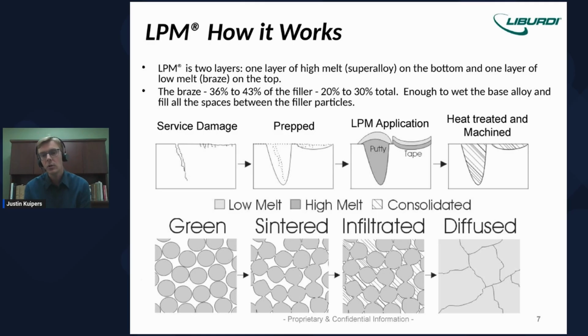We then heat treat to a temperature where our braze has melted, but the part and the high melt powder have not melted. At this point, when our braze becomes liquid, it flows into the spaces between our high melt powder particles and fills those voids by capillary forces. We then go to an even higher temperature where we get consolidation and homogenization of our repair joint, and we get solid grains forming upon cooling.